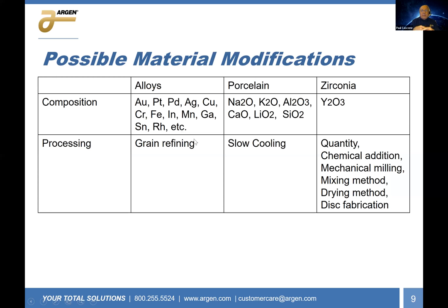Now, as I mentioned, in order to modify zirconia, you really need to concentrate on the processing, which is very different than what we had with other prosthetic materials like alloys or porcelain, where if you wanted to change the thermal expansion of the alloy or the thermal expansion of the porcelain or the translucency of the porcelain or the firing temperature of the porcelain, you had to modify the composition. So we couldn't do much with regard to processing on alloys, and we couldn't do much with regard to processing on porcelain. But we did have the controls with regard to the composition. With zirconia, for a variety of reasons, the only thing we could really control with regard to the composition is the yttria content. And as I said, that could vary between 5 and 10%.